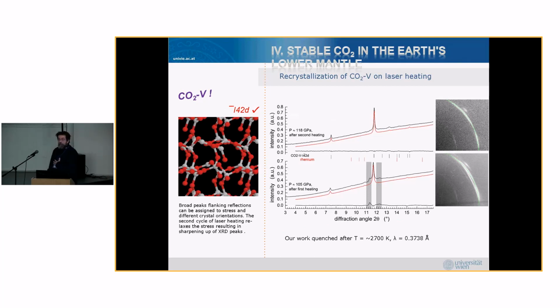The only advantage that we had is we used this magnesium carbonate, and the magnesium carbonate was a pretty good absorber for the CO2 laser, and the normal CO2 no longer absorbs that much once it has transformed into this extended phase, because then the resonance frequencies are shifting, and the CO bond is no longer as good as it would have been for a normal carbonate, and the magnesium carbonate still is.